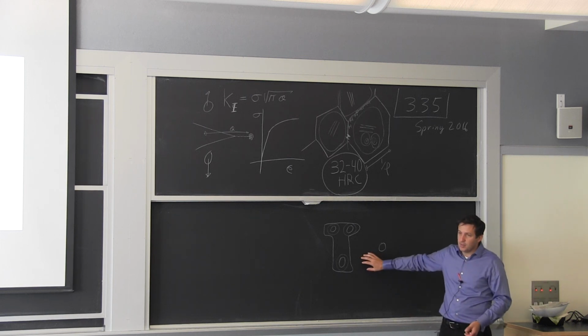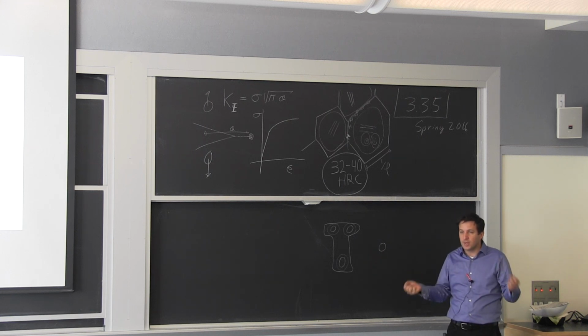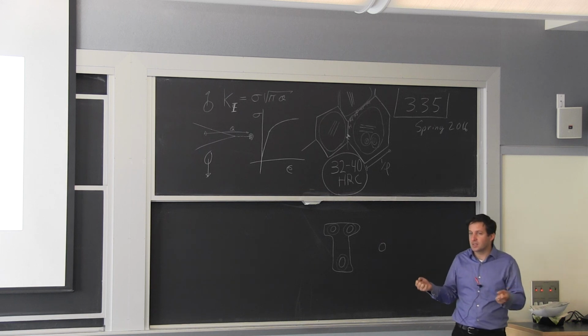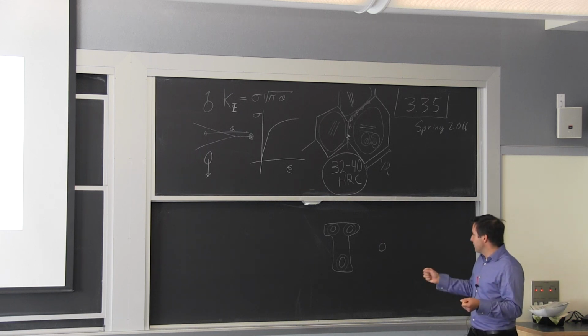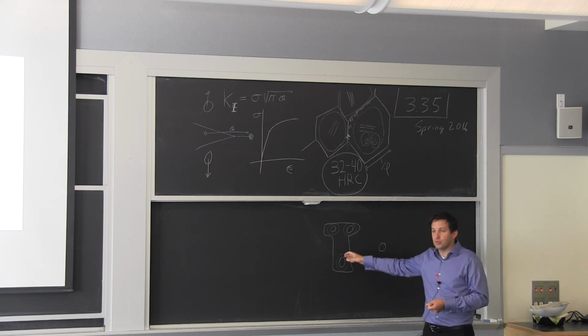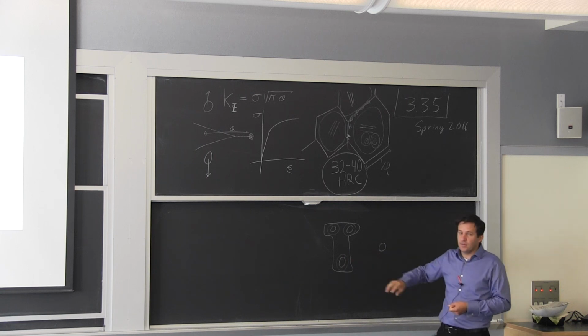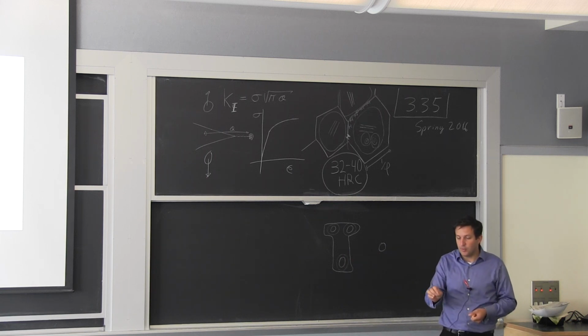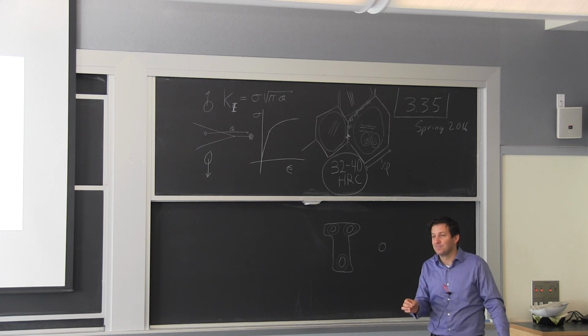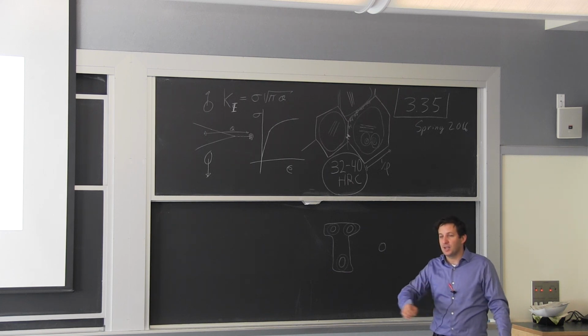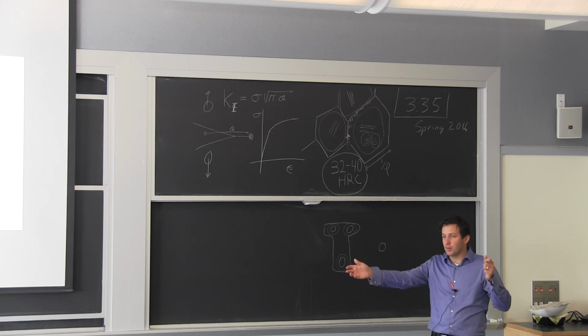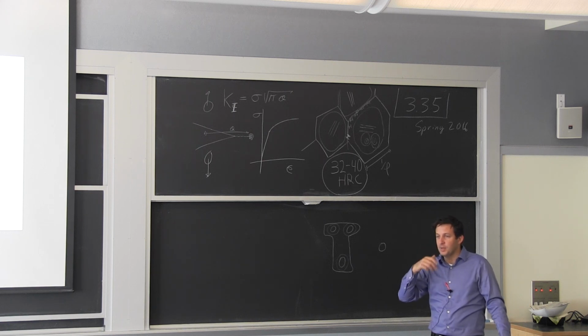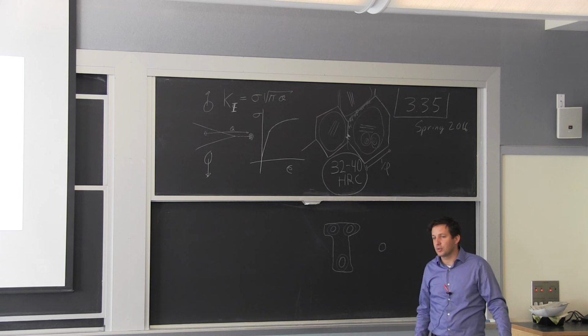If this is a beam in a parking garage, the problem is where do I put my 2 electrodes for sacrificial protection? That's why in practice it's very expensive, because there is only so much moisture in the concrete. What they find is you almost have to put a sacrificial anode every 3 or 4 feet. So it becomes a very complex system if you have a 64 feet beam to have all these cells that act for the corrosion protection.